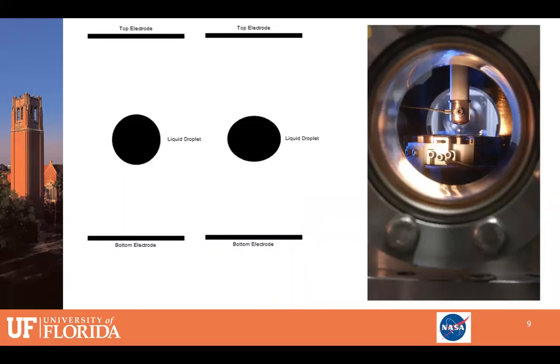On the left, I have an animation, and on the right, I have a depiction of a furnace. So what we have in this animation is a metal that is suspended between two electrodes, one at the bottom, one at the top. And once it's suspended by employing an electrostatic field, it's heated in situ by means of a laser. And as soon as it gets heated and it's molten, provided it's a small mass of metal and also ultimately a small volume, we can create a spherical drop.